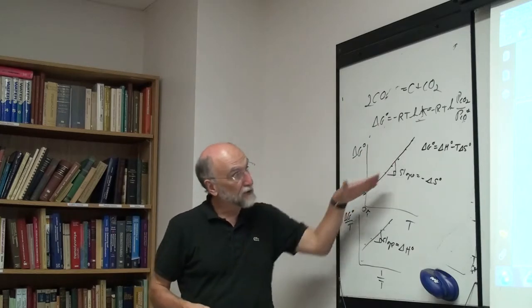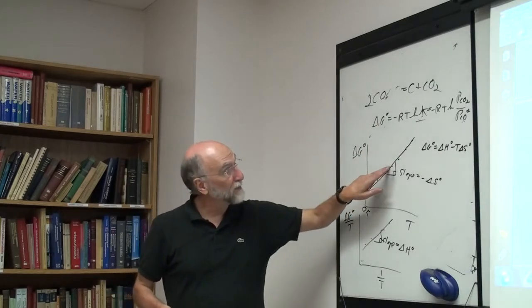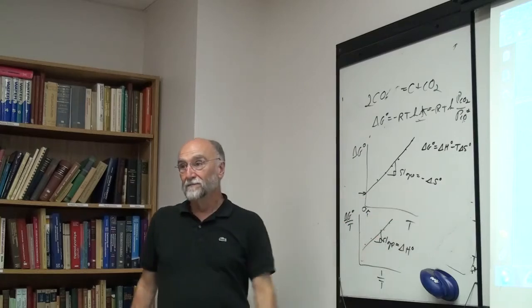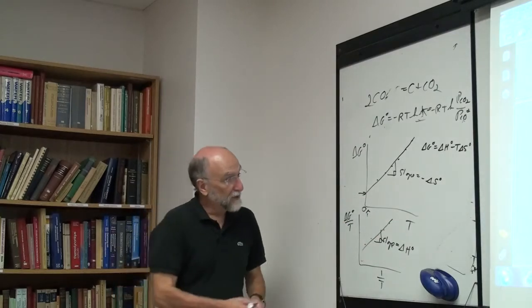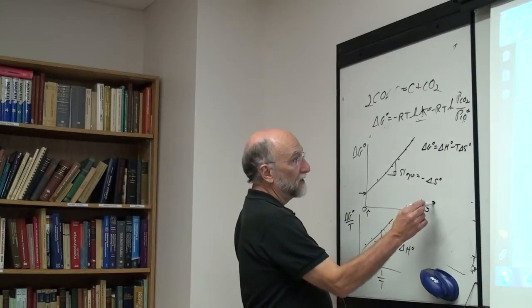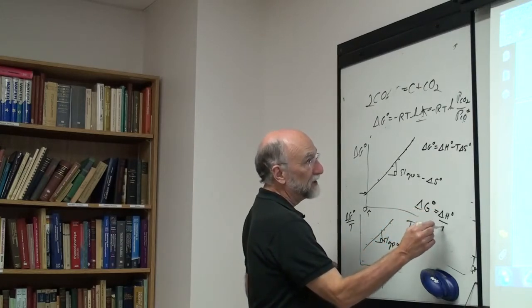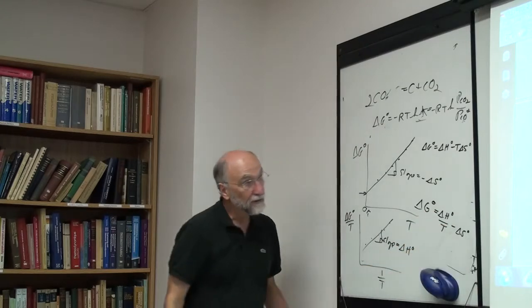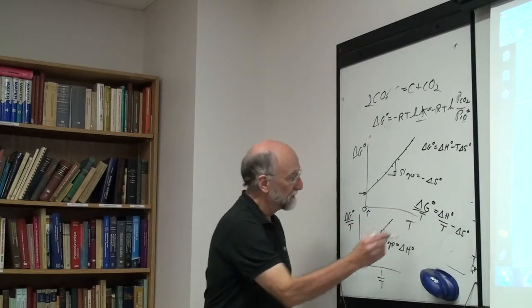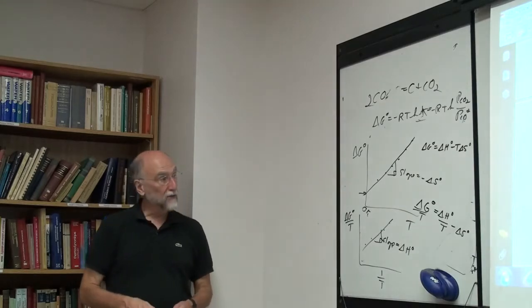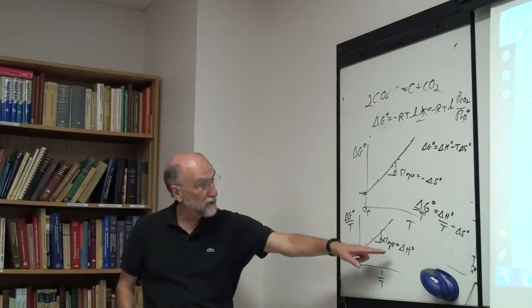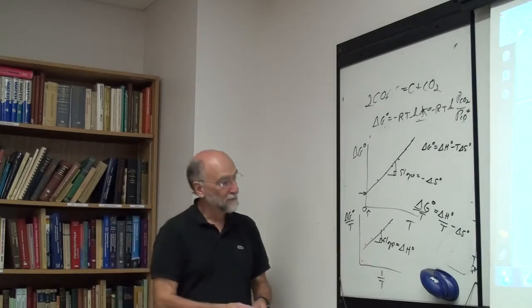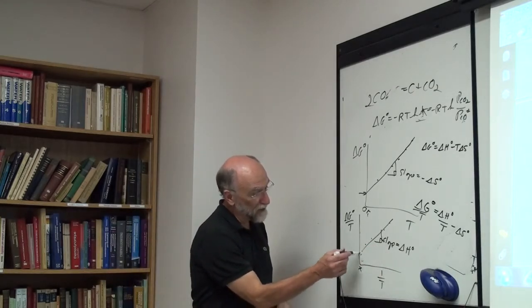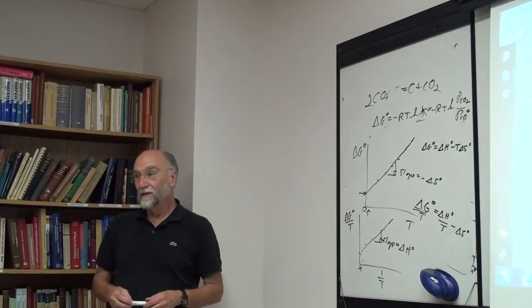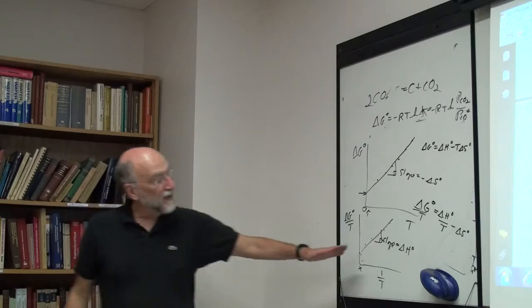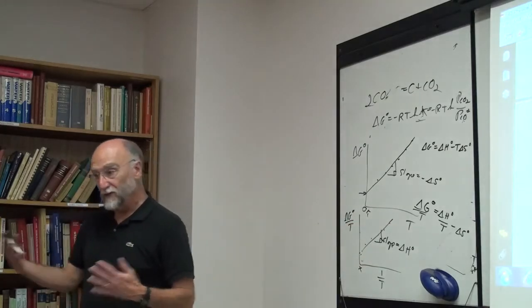In actual fact, of course, it's curved slightly. But even though it's curved, the slope at any temperature is equal to delta S at that temperature. And the same thing here, I could write delta G is delta H over T minus delta S. Sorry, delta G over T is delta H over T minus delta S. So clearly if I plot delta G over T versus 1 over T, the slope is delta H. And now the intercept down here at 1 over T is 0 is going to be delta S if it's a straight line. So this is interesting because this means now I can measure delta H of a reaction without actually doing the reaction.